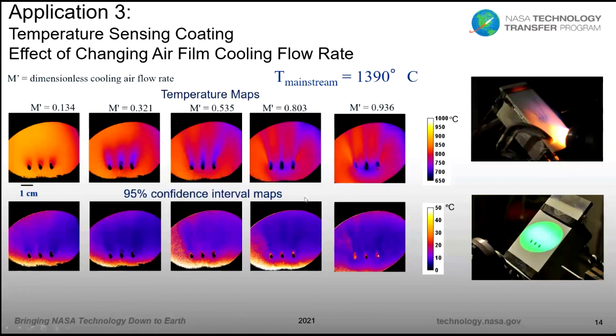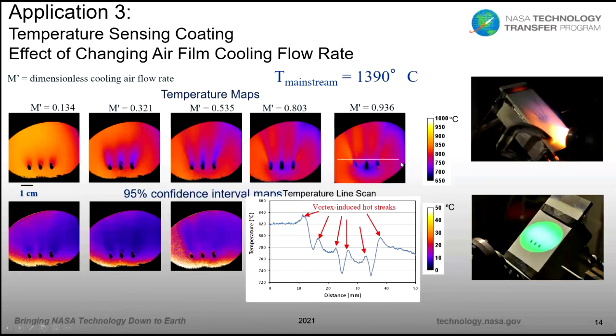Another interesting feature that I hope you can see: there are some bright streaks to the sides of the cooled streaks here. So it's actually hotter at these sides than it is in the uncooled regions. You can see that a little better looking at a line scan across the streaks. You definitely see the cooling streaks, but to each side you see it actually increases in temperature, here about 20 degrees C hotter than the uncooled region. This is something undesirable, and it is known that this can happen because an air jet can produce vortices at its sides, and this can push down hot gas against the surface. So this is important to know, so you can pick cooling conditions that don't produce these hot streaks.